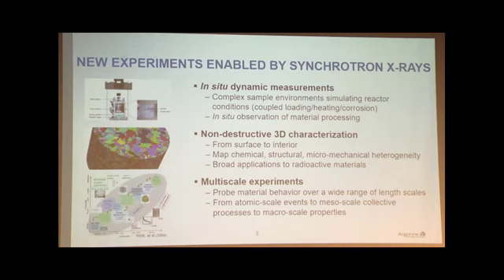For example, the experiment can be done in situ, and with the synchrotron X-ray, we can build very complex sample environment. This is particularly important and useful for studying nuclear material because we want to simulate a reactor environment, which has to involve loading, temperature, and corrosive environment.